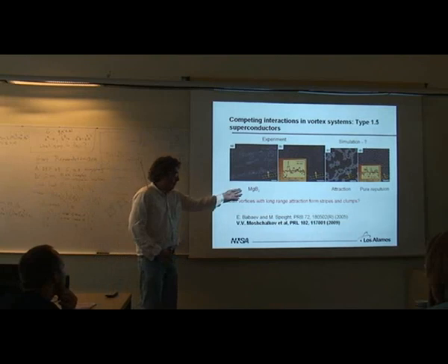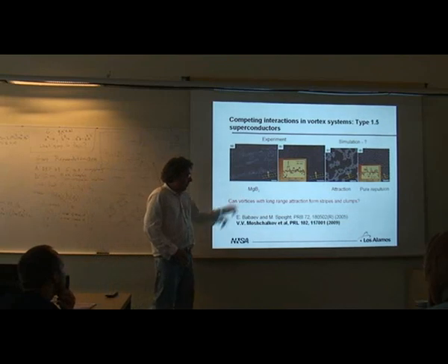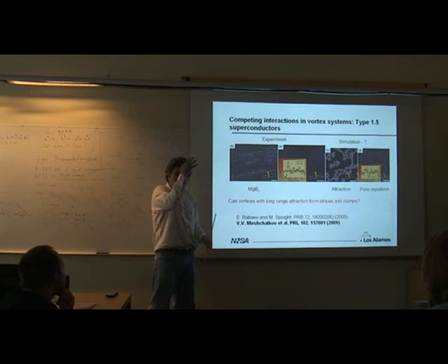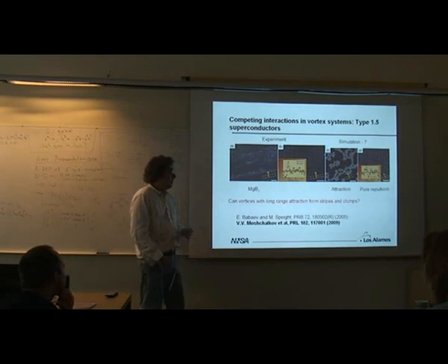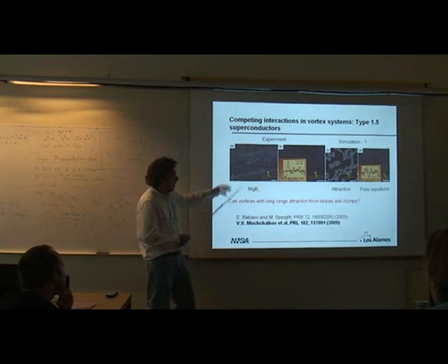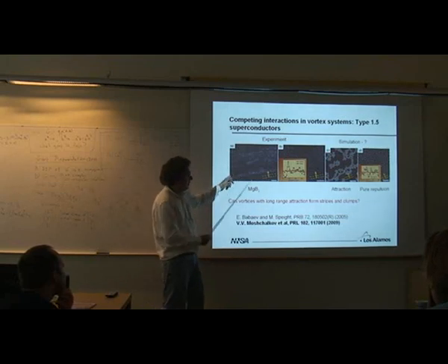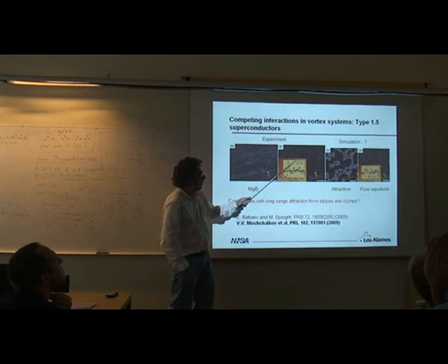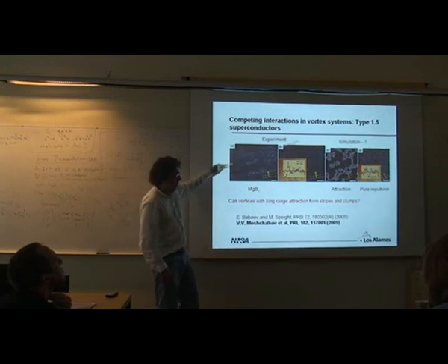One example where this system could be realized is magnesium diboride, a two-band superconductor, and you assume one band is type 1, and the other band is type 2. And then here's a low field image of the system, and you get these funny sort of stripe phase. Over here, I believe, is niobium, and then you get the more uniform vortex size.